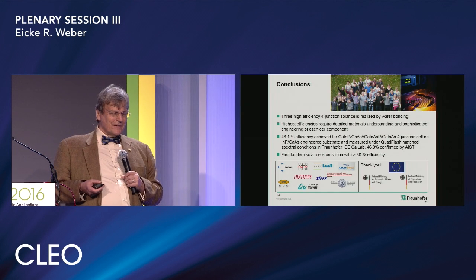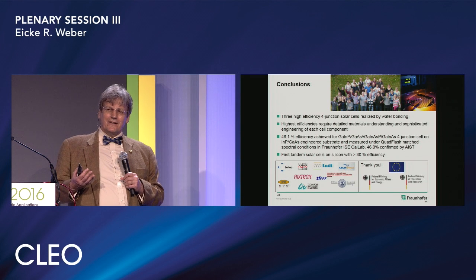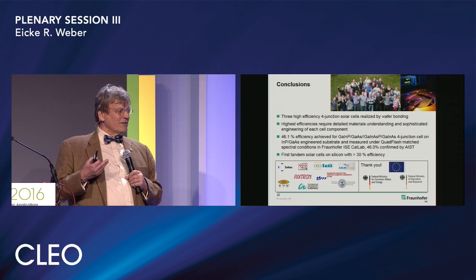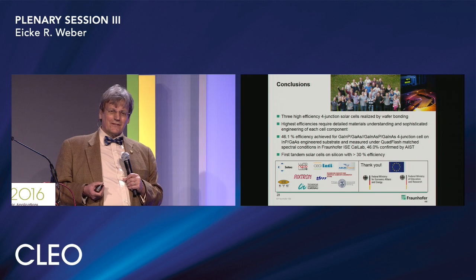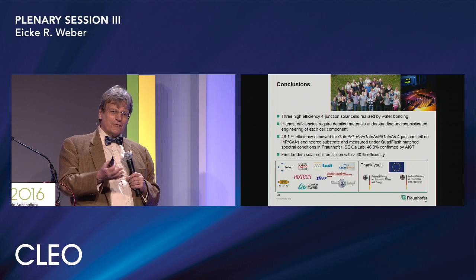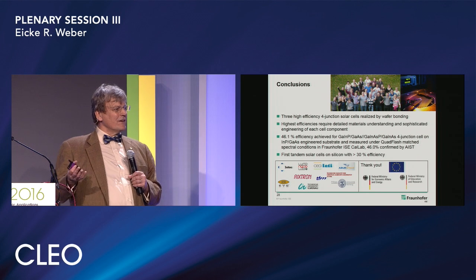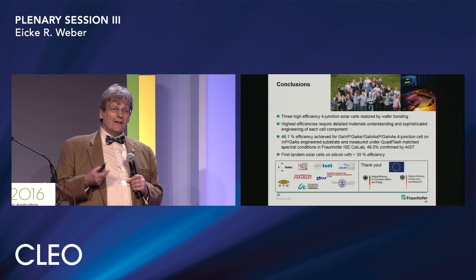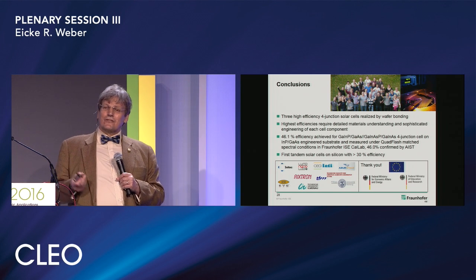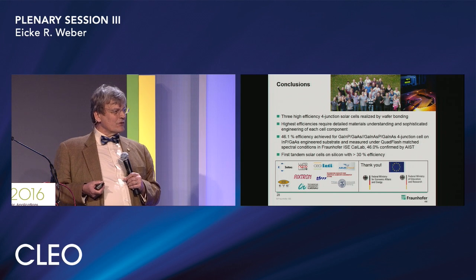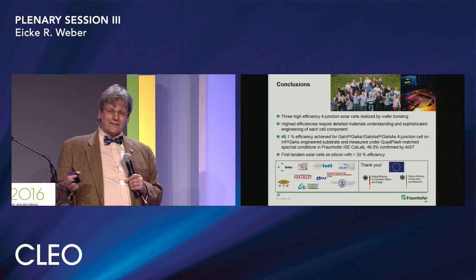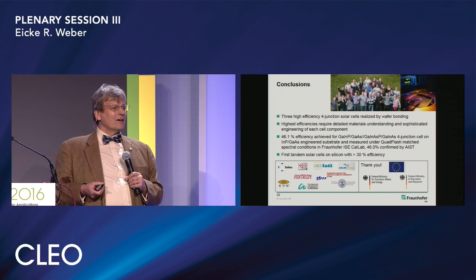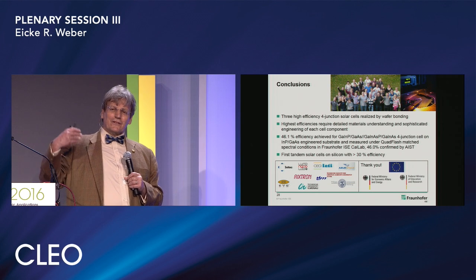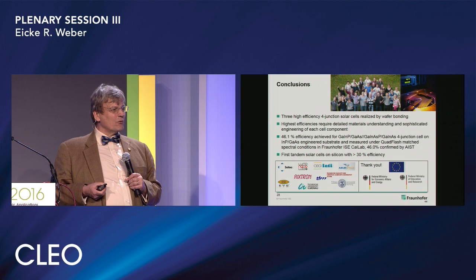I hope I could show you that the understanding of materials combined with the understanding of processing technologies, and there the big advantage is the combination of experiences from silicon technology, from III-V technology in the best way, using the III-V deposition experience which we have, growing lattice matched as well as strained layers, using wafer bonding coming out of silicon technology. This gives us a tool chest, and you saw it in the structures which I presented to you, which allow us then to really come forward and exceed everything what was known up to now and really reach the efficiency limits that theory sets us.